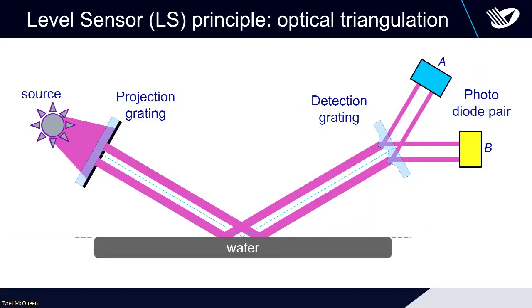So what you're actually doing here is translating a nanometer height variation into an intensity measurement. You can measure intensity over orders of magnitude with a high accuracy. And that's where this nanometer sensitivity comes in. It's not a resolution in that sense. You're still projecting micron pitch gratings on the surface, but you can measure very accurately if there's a very slight position shift that translates into an intensity shift. Now, this of course looks very simple, but it's never that simple in real life.